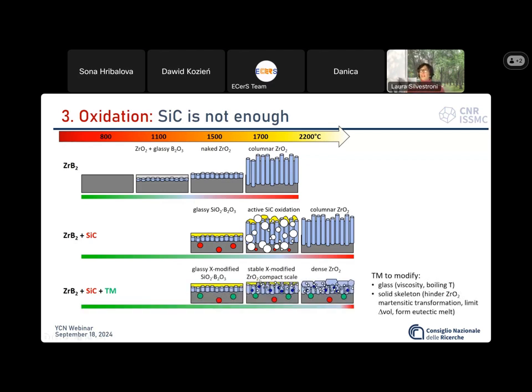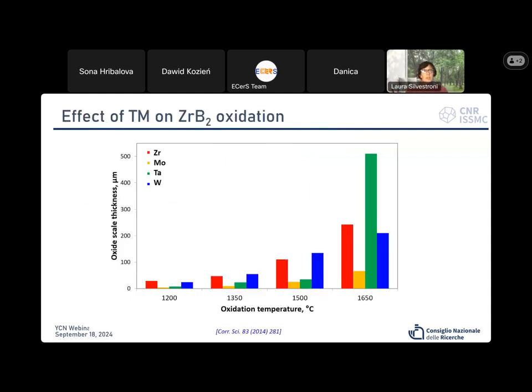Therefore, we decided to add some transition metal to modify the glass viscosity, boiling temperature, and saturation. And the transition metal could modify also the solid skeleton, the zirconium oxide, hindering the martensitic transformation, limiting the expansion of volume, and forming a eutectic melt that could slow down the oxygen penetration within the core. So here you can see how the addition of a transition metal strongly impacts the oxidation behavior.